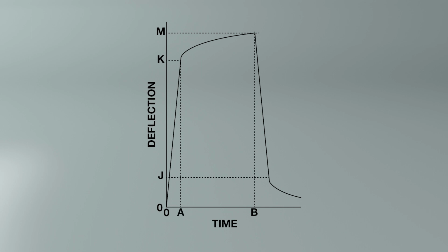When the force is released at time B, the deflection quickly goes to point J, then creep recovery occurs and the deflection goes back toward zero with about the same curve shape as the loaded creep inverted. Creep continues as long as a force is applied, but the rate of creep decreases significantly with time. It is typically measured and specified for a 20-minute interval. To illustrate the concept, the creep in the first 20 minutes is about equal to the creep in the succeeding